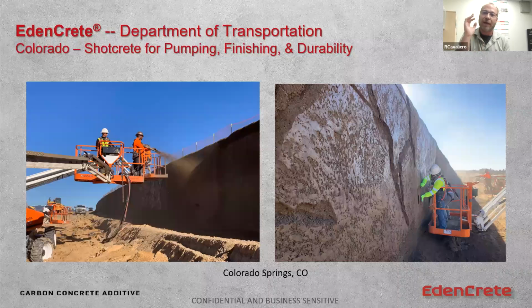Because we created a mix that at higher strength will lower cement, they only request one mix. It's the EdenCrete mix. And it's a mix that makes 5,000, but has the cement content of the 4,000. And ultimately it stamps and it adheres for the structural. It solves all the problems, removes the logistical headache, and ultimately saves problems out on the job.